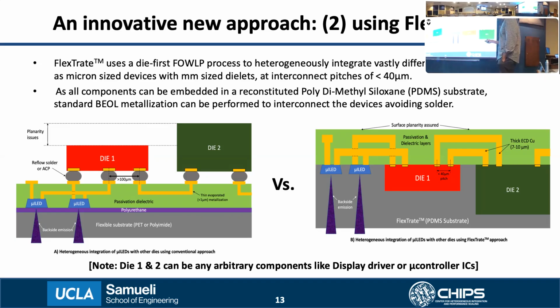So in our approach, we do not use any solder. We directly metallize on the pads, and so we can bring the devices much closer to each other and attain much higher integration densities. And by avoiding the use of solder, we can also integrate components that have much finer pad pitches.